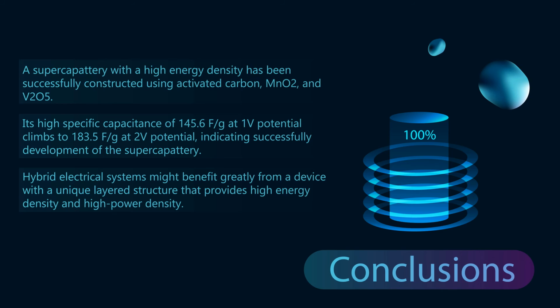In conclusion, three main points have to be mentioned. Firstly, a supercapattery with a high energy density has been successfully constructed using activated carbon, manganese oxide, and vanadium oxide. Secondly, using a potential window of 1 volt, the constructed device exhibits a high specific capacitance of 145.6 farad per gram, which rose to 183.5 farad per gram at 2 volt applied potential.